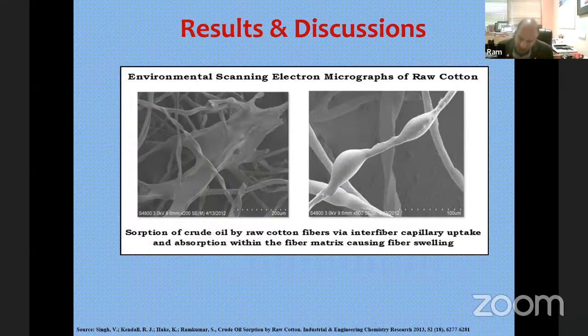What is the mechanism? We used an environmental scanning microscope, and these were among the first images on real crude oil. There is a lot of work done on synthetic oil, motor oil, and cooking oil, kitchen oil, that's all fine. But crude oil, real crude oil, what happens first? The mechanism is adsorption. The oil gets adsorbed onto the surface of the cotton and forms a film. And since low micronaire cotton is immature, the fibers are much finer. When they are much finer, the surface area is more, so they are able to adsorb